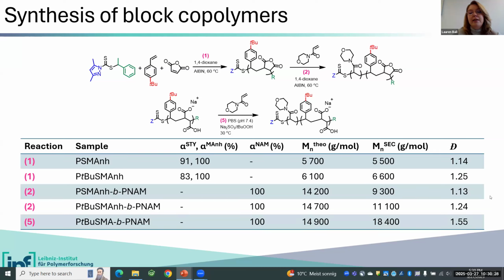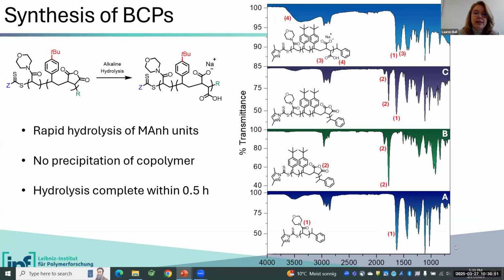So we have a copolymer sample with very similar chain lengths and composition, which is exactly what we want for very well-defined solution properties. The alternative synthetic strategy, where we ring opened our macrochain transfer agent first and then chain extended in aqueous conditions, also proceeded with high monomer conversion, but slightly high dispersity, which I'll discuss in the next 2 slides.